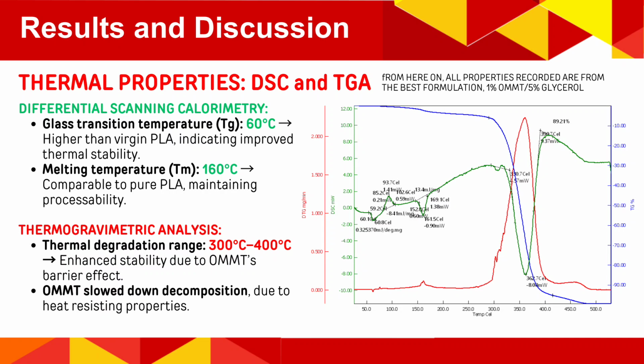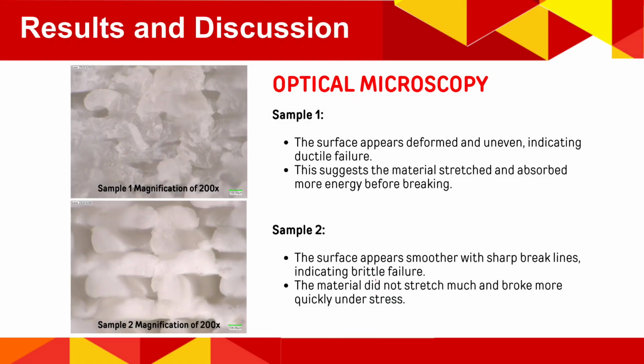for long-term use. To examine the fracture behavior, we conducted optical microscopy on a tensile sample of the best formulation. The images show that glycerol improved flexibility, reducing sudden failure, while nanoclay dispersion influenced the fracture behavior. Sample 1 had rougher fracture surfaces, suggesting better energy absorption, whereas sample 2 had more brittle characteristics. This confirms that our formulation enhances toughness and impact resistance, crucial for orthotic applications.